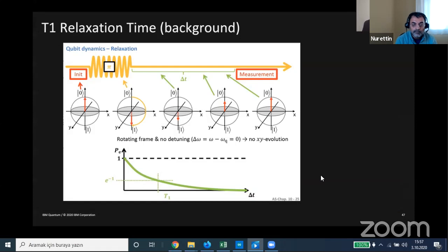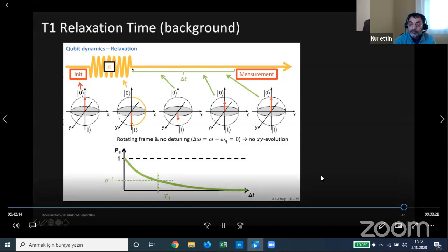We then wait an amount of time delta t and measure the state of the qubit. In the limit of very long time, the 1 state will relax all to 0, and that's what's shown in this graph here. So this graph shows the probability of being in the 1 state. At 0, the probability is 1 because we just did the pi pulse. But as we increase the amount of time, you can see the qubit starts to relax.